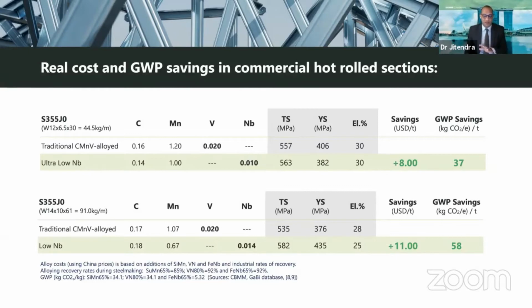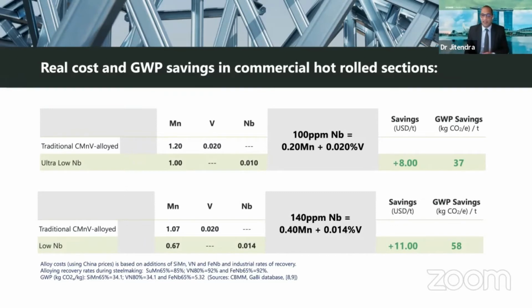And that's part of the GWP I'll be talking about in my second presentation this morning. But you can see that here, there are significant savings to be made under the current climate, particularly because ferroalloy prices of manganese and also vanadium are at high levels and continue to be going in that upward trajectory. And so here, just summarizing that, by adding 100 ppm or, in the lower case, slightly higher at 140 ppm niobium, we're able to substitute some degree of manganese and vanadium. This is without making any changes to the rolling conditions; it's purely a change to the alloying mix itself.